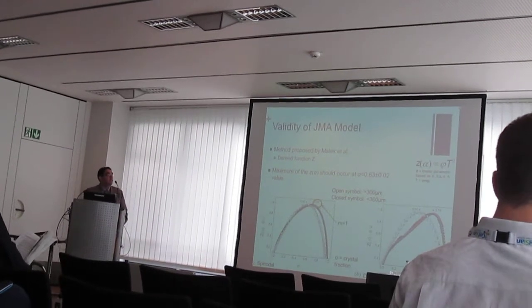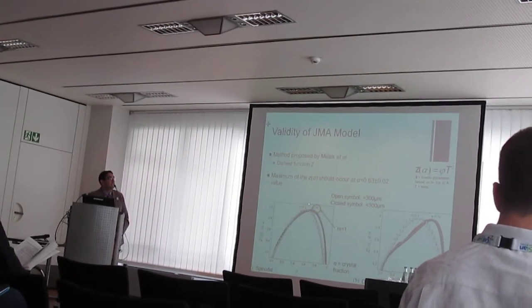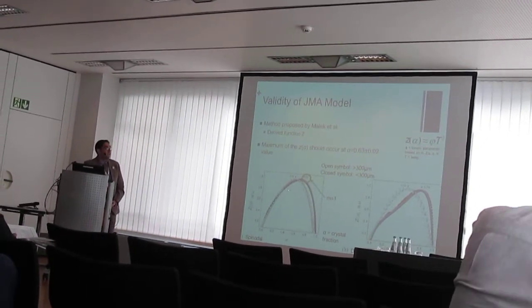So when we calculated the maximum of the z of alpha curves, we saw that both for spinodally separated glass and the droplet separated glass, the maximum of the z of alpha curve was not in the range of 0.63 plus or minus 0.02. It was actually 0.56 and 0.55 respectively.